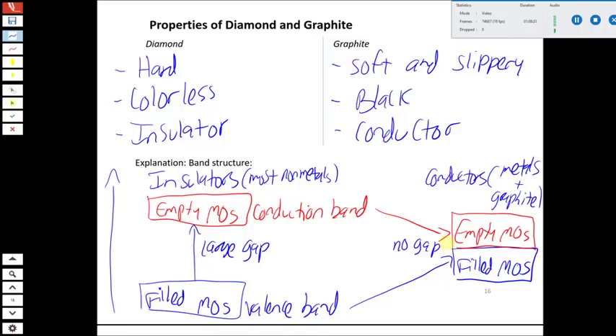The reason diamond and graphite are different is, again, think back to molecular orbital theory. If we formed a sigma bonding and a sigma anti-bonding orbital, that would have a pretty large gap between them, but a pi bonding and a pi anti-bonding have a smaller gap. Remember that the distance between the bonding and anti-bonding orbitals depends on how strong the overlap is. Sigma overlap is very strong. You get a large gap between bonding and anti-bonding, which leads to a large band gap in diamond. But when you have graphite, the frontier molecular orbitals are all pi orbitals. As we said, there's pi bonding in graphite. The pi bonding and anti-bonding orbitals are much closer to each other. They don't split nearly as far, and so that shrinks the band gap and gives you electrical conductivity. So it's that difference in bonding type, sigma versus pi, that leads to this difference in electrical conductivity for diamond and graphite.